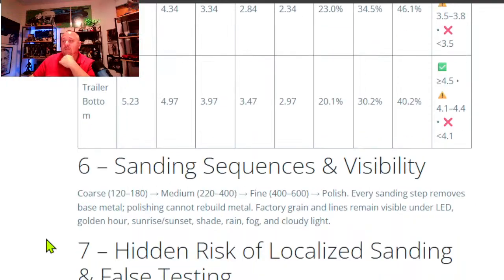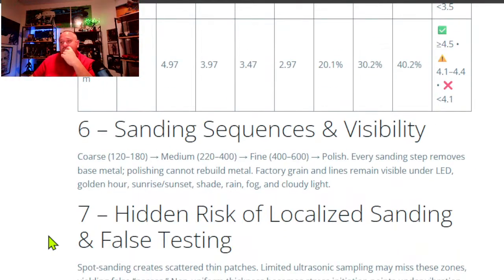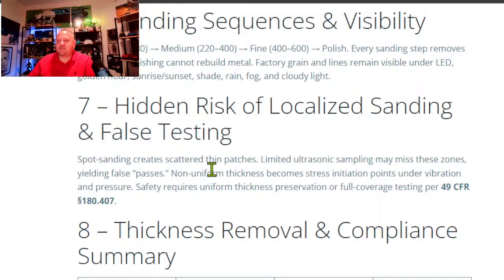It's just not good. Sanding sequences and visibility. Coarse is 120 through 180, medium 220 through 400, fine is 400 to 600. Then typically what people are pushing is polish. Every sanding step removes base metal. Polishing cannot rebuild metal. Factory grain and lines remain visible under LED, golden hour, sunrise and sunset, shade, rain, fog, and cloudy light. So there is no such thing as perfection, and we're going to get into that. There is no such thing as a surface being absolutely perfect. Never.